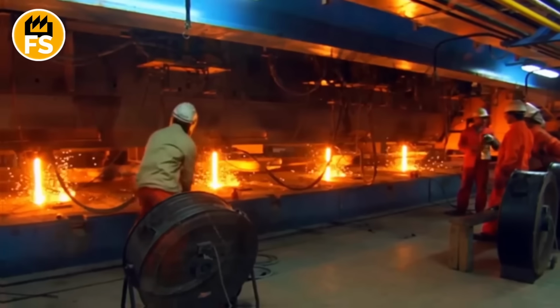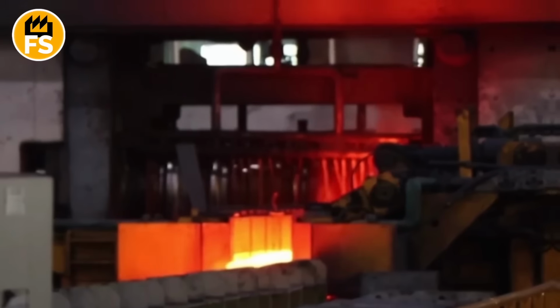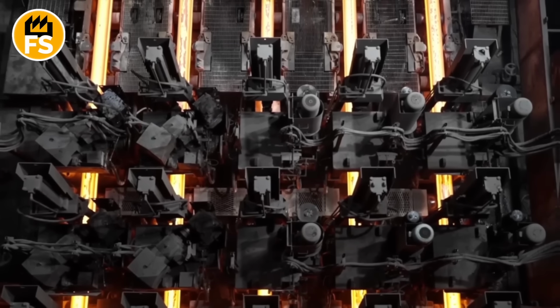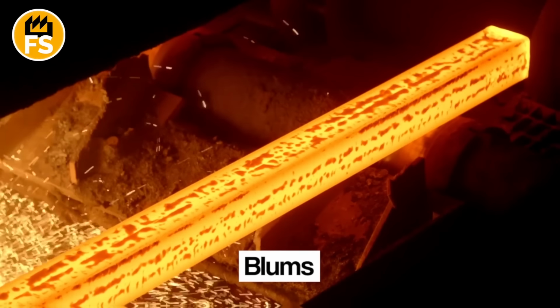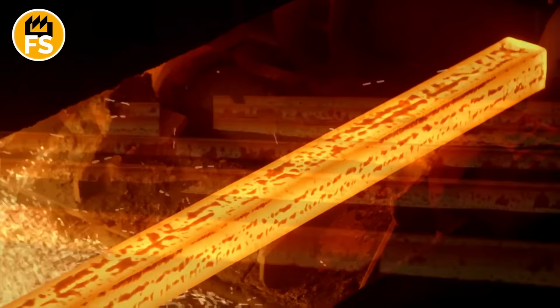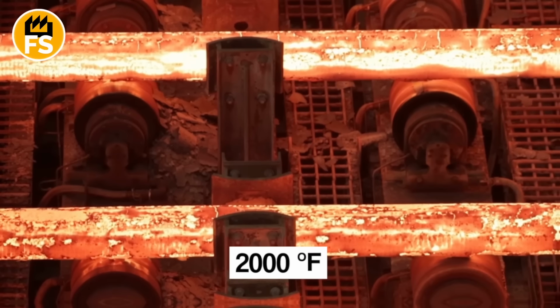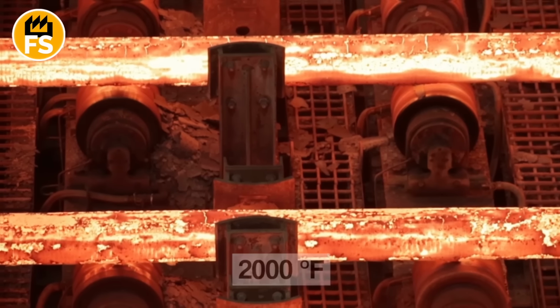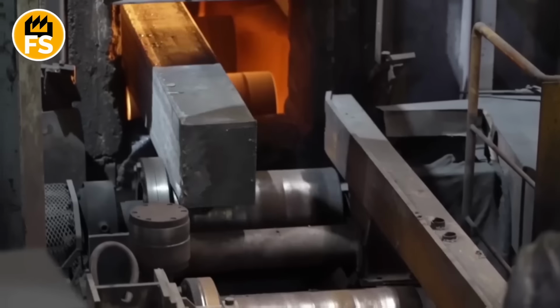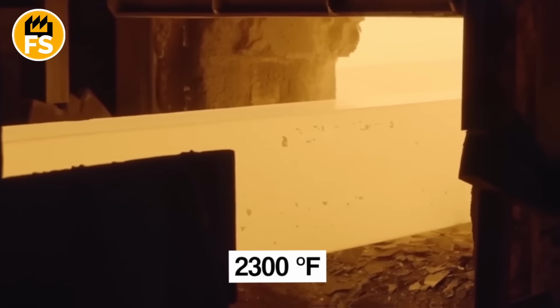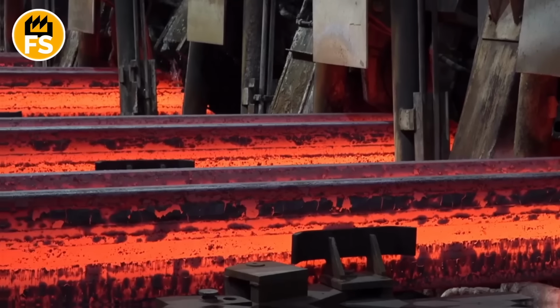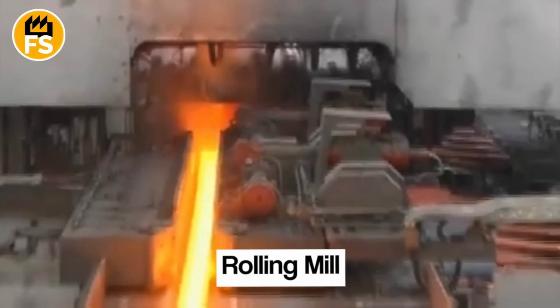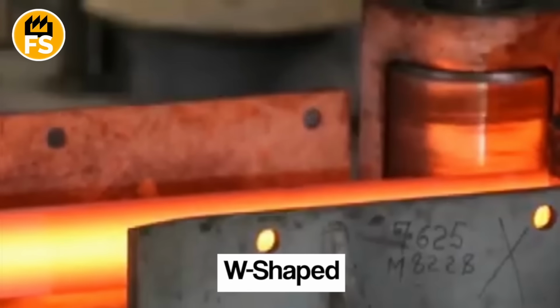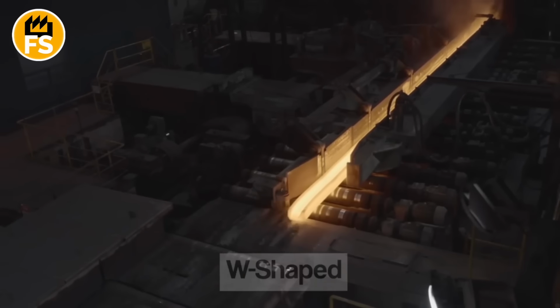From the oxygen furnace, the molten steel flows into continuous casting machines, where it starts taking solid form, pouring into water-cooled molds that shape it into thick rectangular slabs called blooms that are about 10 inches thick and 3 feet wide. These blooms come out still glowing bright orange at around 2,000 degrees Fahrenheit, and they immediately go into reheating furnaces where they're brought back up to exactly 2,300 degrees before heading to the most important part of the whole process. The rolling mill is where these thick blooms of steel get transformed into the distinctive W-shaped beams that you see in construction, and when you watch this process, it's absolutely incredible.